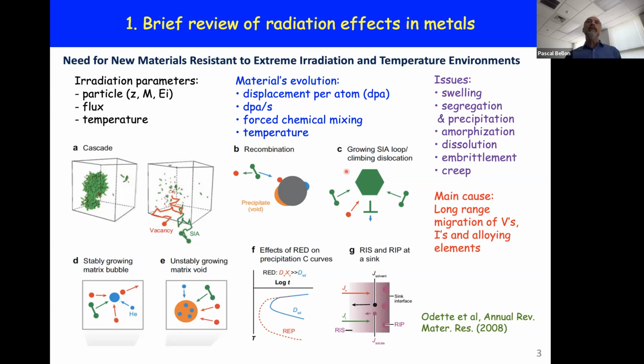So some of the point defects may cluster and form dislocation loops, which may, under applied stress, climb and contribute to creep. Other point defects may co-cluster with helium atoms and form bubbles, which may contribute to embrittlement. Then point defects, also vacancies, may cluster and form voids, leading to swelling.